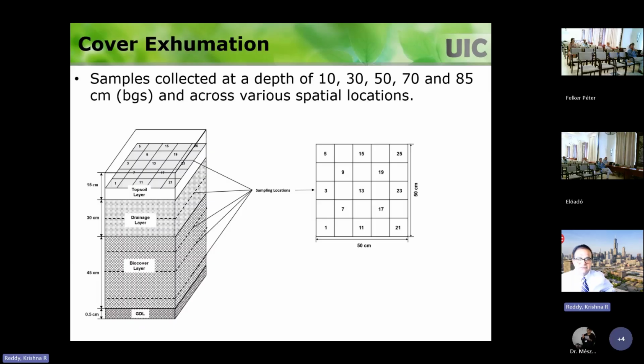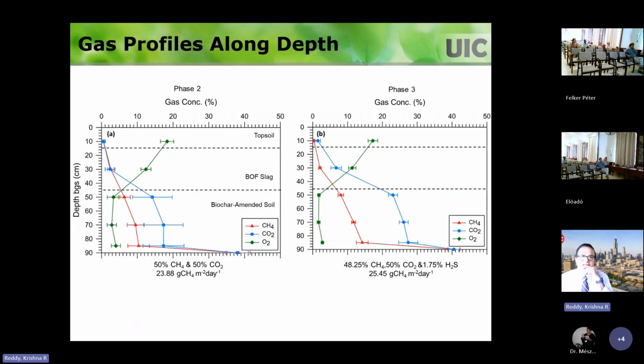So the good thing is, we had that transient data, but also at the end of the testing, we were able to exhume the samples, collect them, and do testing to look at remaining oxidation capacity and carbonation potential. Because the tank is really large and you can collect the samples, you can get the spatial variation also in this one compared to a simple cylindrical setup. You assume 1D and uniform conditions there, but here the gas flow could be changing spatially, so you can get interesting results.